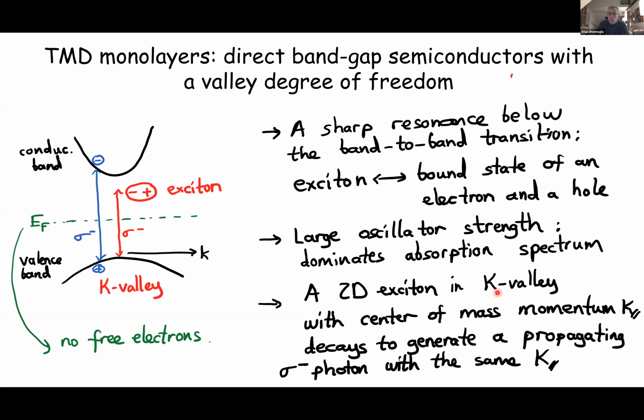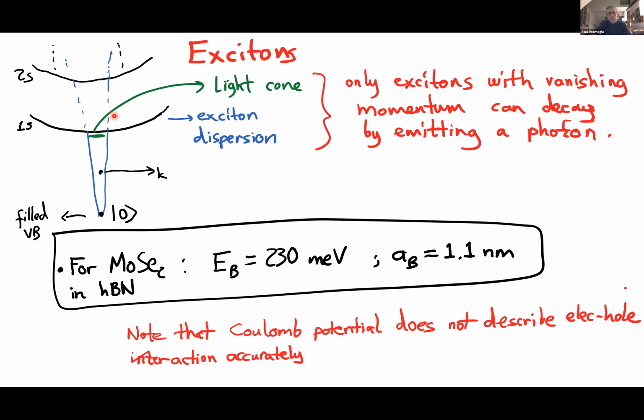And one other important point that I would like to make is that if we assume an ideal disorder-free system, the excitons that are generated in the system have translational symmetry, and therefore momentum would be a good quantum number. And when an exciton decays to generate a photon, it generates a photon with the same in-plane momentum due to momentum conservation, which in turn means that only low momentum excitons can decay. So to highlight this better, I would like to go from the single particle dispersion to a dispersion of excitons. Okay, so in this case, what I'm plotting is the energy dispersion of different kinds of excitons that we can generate. What is most important for us is the 1s exciton.